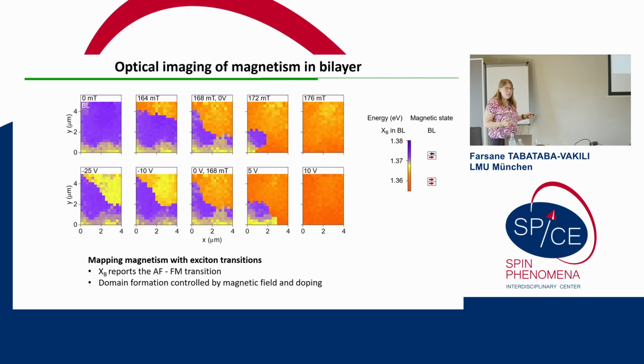And then, if we go to a magnetic field close to the critical field, here 168 millitesla, and we apply electrostatic doping, we observe the same magnetic domain formation across the metamagnetic transition. Just across a smaller range, because we have a smaller range accessible with doping. So, in this material, we can control the magnetic domain formation by both magnetic field and doping, which is kind of neat. And it's not very homogeneous, which may or may not be great, but at least it allows us to visualize this.